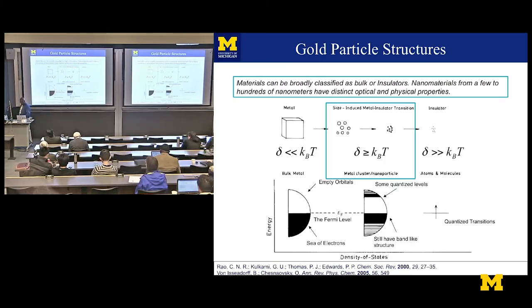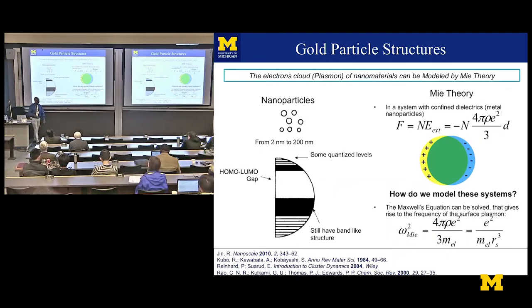People have looked at these kinds of things and found that if you use simple Mie scattering theory, which most people do to talk about particles, we don't have to talk about equations, but generally speaking, this scattering approach, which is based on the dielectric, can model the bigger particles. From Maxwell's equations you will get a surface plasmon at a certain frequency, depending on the dielectric of the material and other properties. And that's well understood. But what happens if you make the particle smaller?